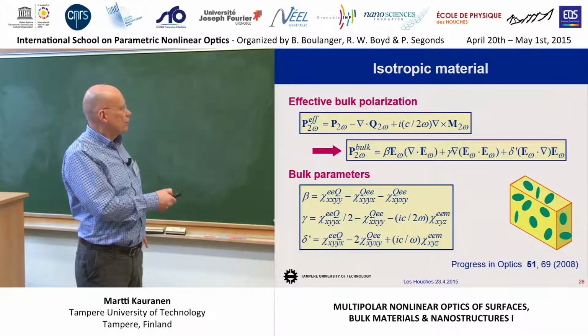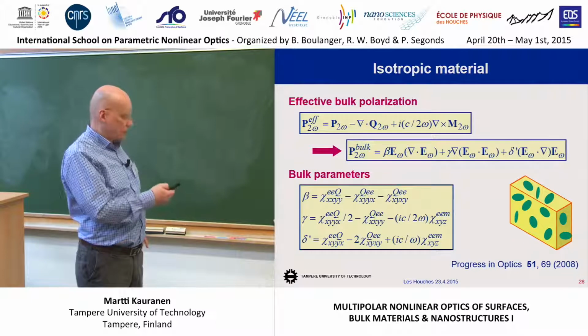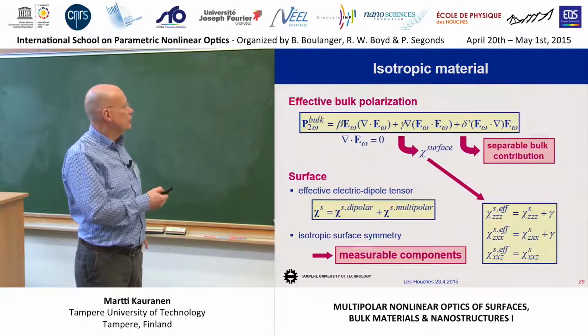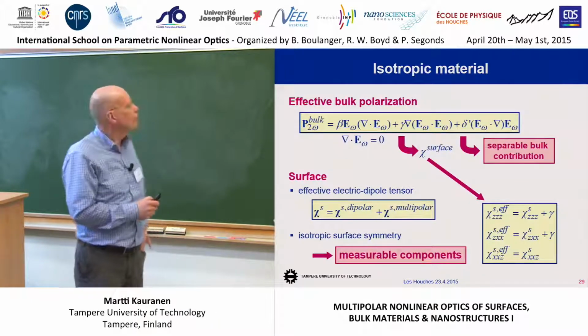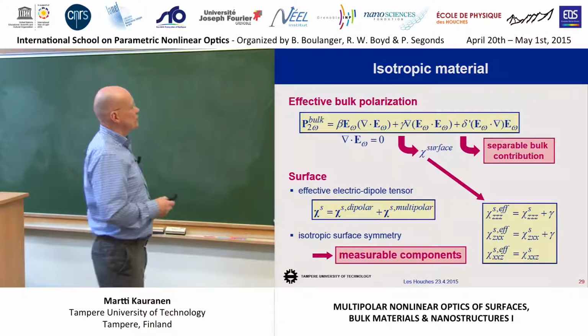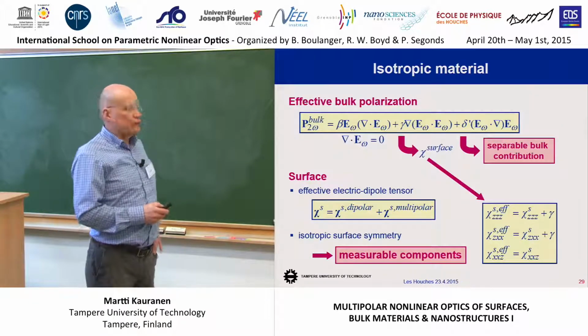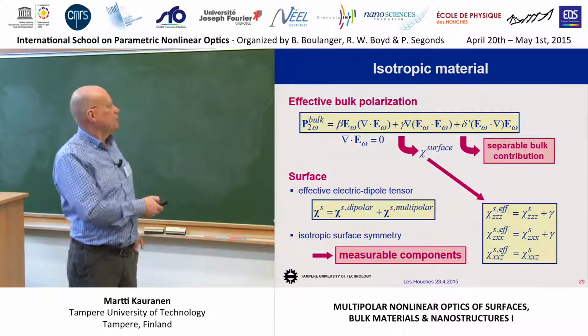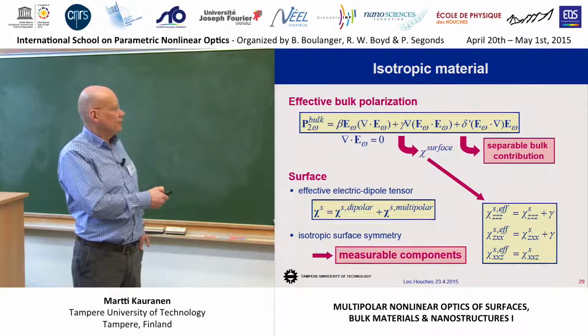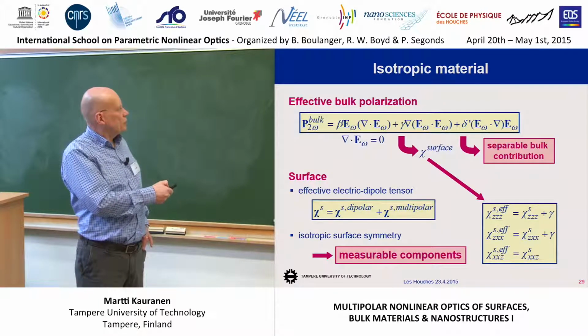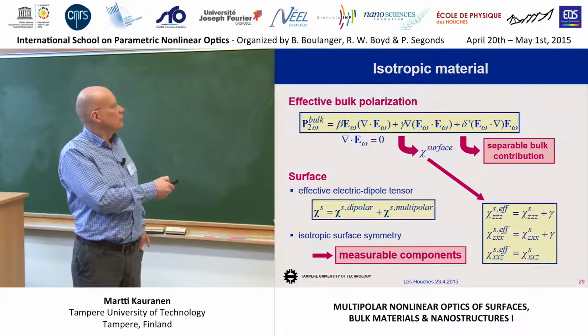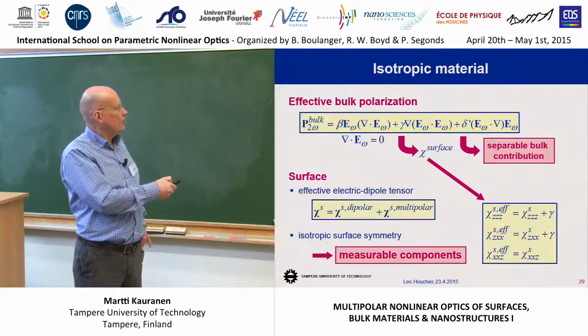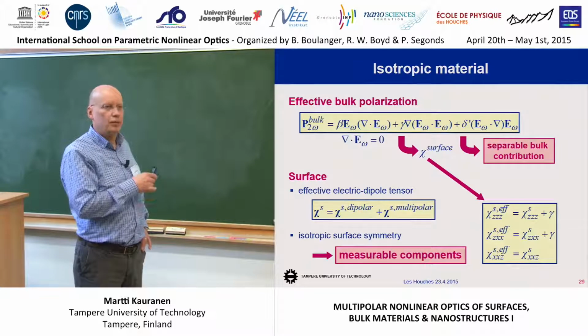And to have a closer look at this expression, let's use some of the symmetry rules again. So the material is isotropic, and it turns out that in an isotropic material, del dot E is always vanishing. So this beta term, although it's formally here, the beta parameter is non-vanishing, but this interaction does not occur due to the symmetry of the material.